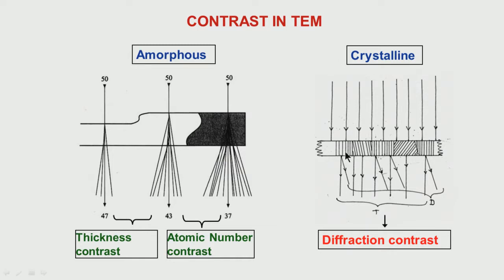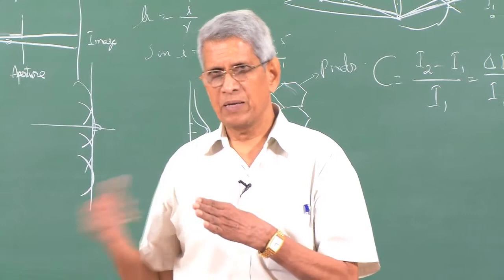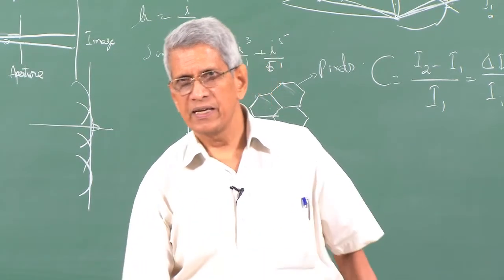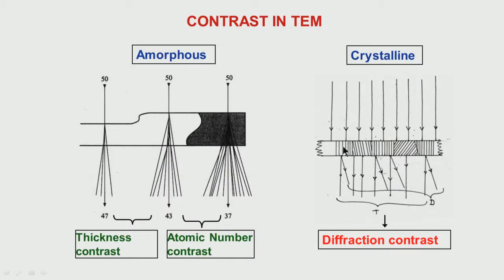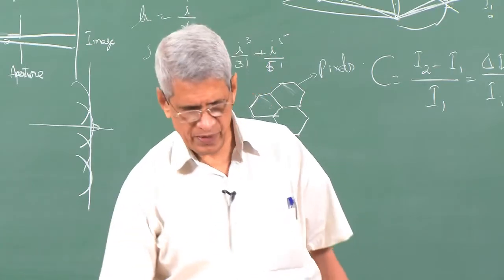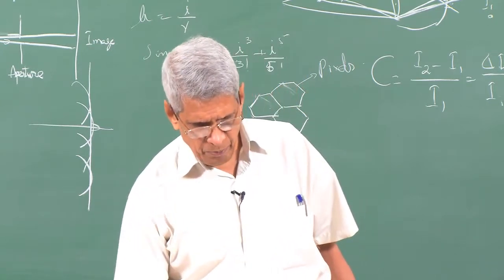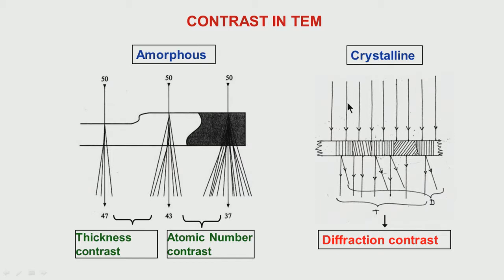That means that, conversely, in the primary beam direction, as the beam passes through, for some orientation of the sample the intensity of the primary beam is quite high. As the sample is being tilted, the intensity changes. That can happen because in a polycrystalline material, different regions are oriented in different ways with respect to the beam. So we find that intensity variation will come. Why is this occurring? Because especially in an electron microscope, the Bragg angle is less than 1 degree. So it's almost the planes which are parallel to the beam that give rise to diffraction. Depending upon how the planes are oriented, from region to region in a grain, there will be a variation in intensity. Depending upon that, in the transmitted beam also, if you look along this direction, you find that there is a variation.